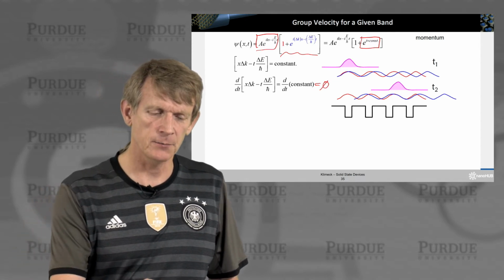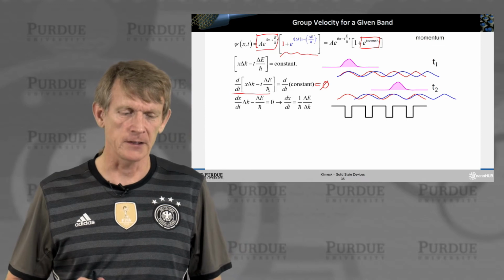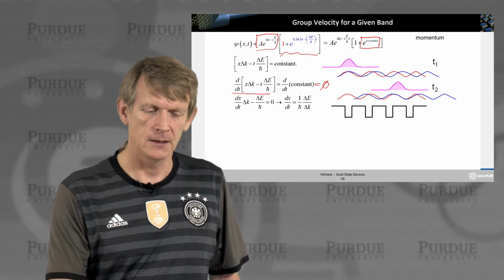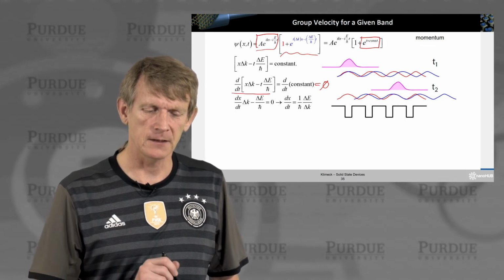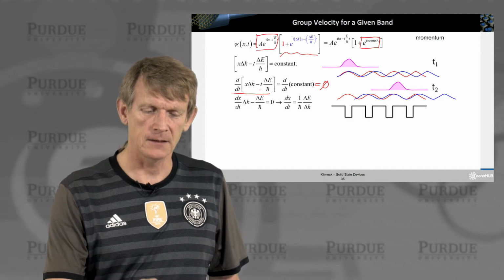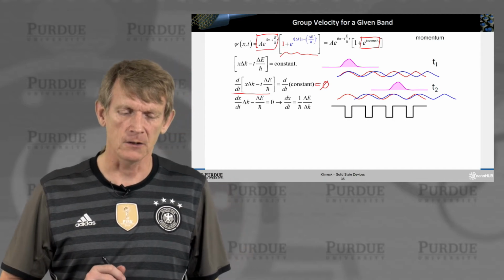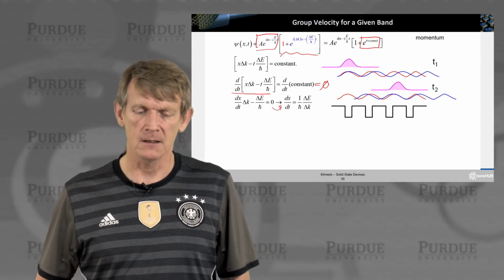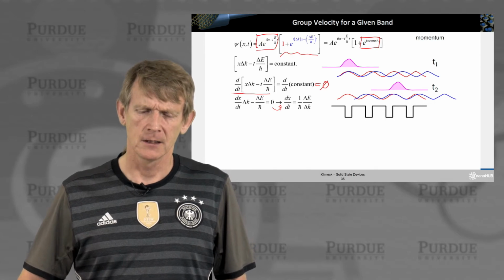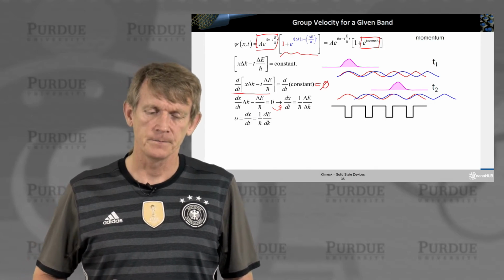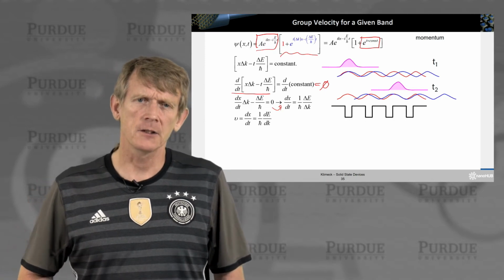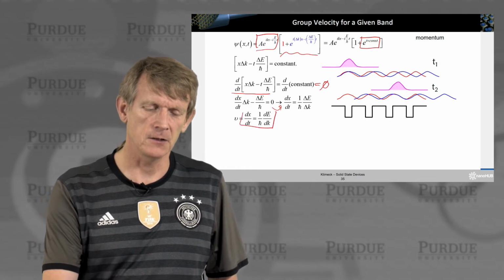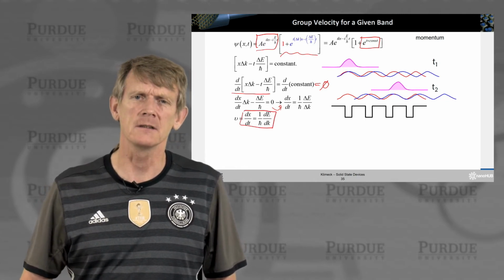So if we take the time differential of this, we know it's dx/dt times delta k minus delta E over h bar, and that needs to be 0. So we can resolve that here into delta x over delta t equals 1 over h bar delta E over delta k. All right. Now, dx/dt you can also define as the velocity. And if that's the case, then you have dx/dt, or the velocity, as 1 over h bar dE/dk.